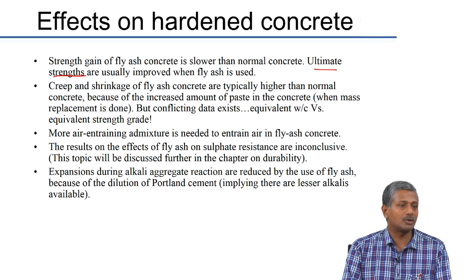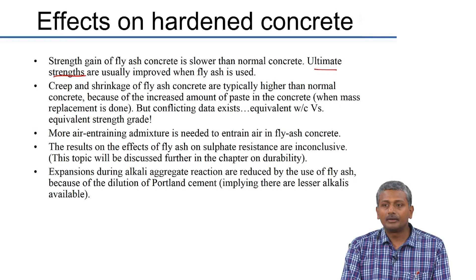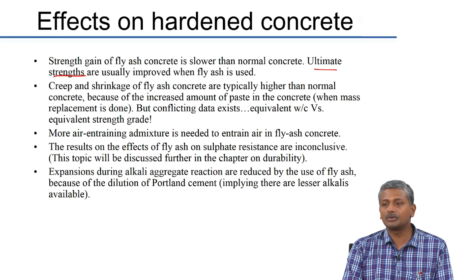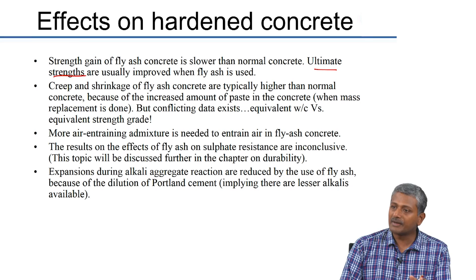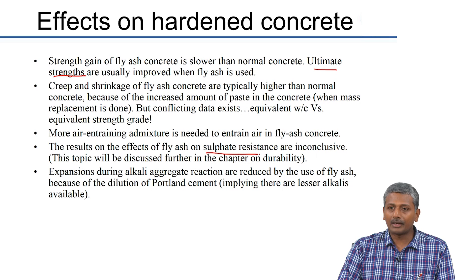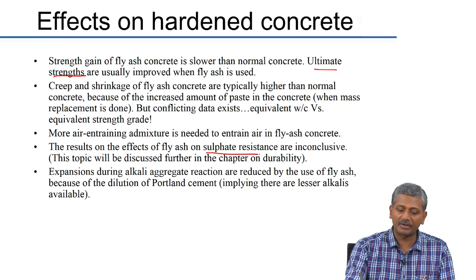When air entraining concrete with fly ash, you generally need a little extra air-entraining agent to entrain the same quantity of air, again because of the presence of unburned carbon which interferes with the air-entraining agent. Sulphate resistance results are inconclusive and will be discussed in the durability chapter. Like all pozzolanic materials, expansion due to alkali-silica reaction can be reduced significantly when fly ash is used as a replacement for Portland cement, because replacing Portland cement reduces the alkali content in the system, leaving less potential for ASR.